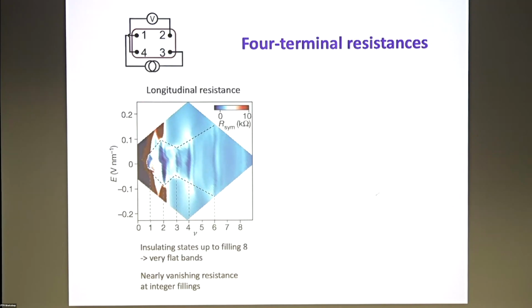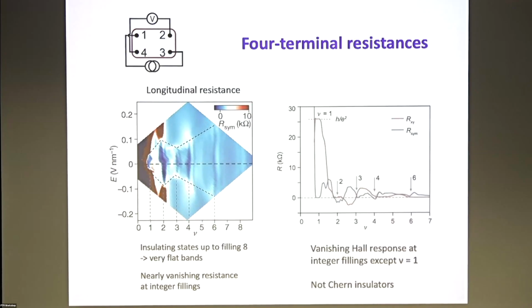So this is an electric field and filling map of the longitudinal resistance. You can see filling one state not very clearly, so let me just show you the line cut at the zero electric field region. That's basically the region we are mostly interested in. At filling factor 1, you get 0 Rxx but a quantized Rxy, that's the Chern insulator. And you can also see there is a fractional Chern insulator around filling factor 3.5 with a weak Rxy plateau here, not very well quantized, but it is there.